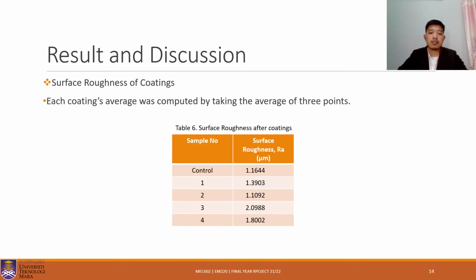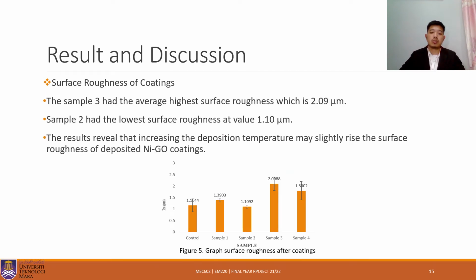That is surface roughness of coating. Each coating average will be computed by taking the average of 3 points. Table number 6 shows the surface roughness of the coating for all samples. Data from table 6 were plotted in the graph in figure 5. Sample 3 had the highest average surface roughness, which is 2.09 micrometer, while sample 2 had the lowest surface roughness at a value of 1.1 micrometer. The result revealed that increasing the deposition temperature may slightly raise the surface roughness of deposited nickel graphene oxide coatings.